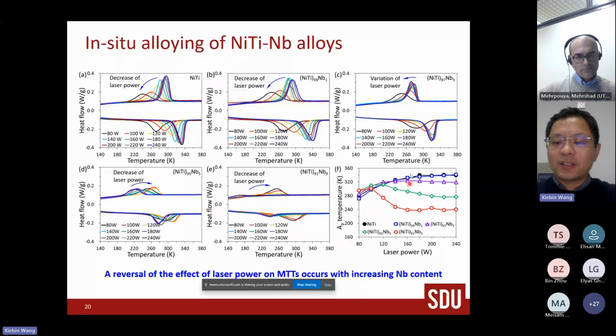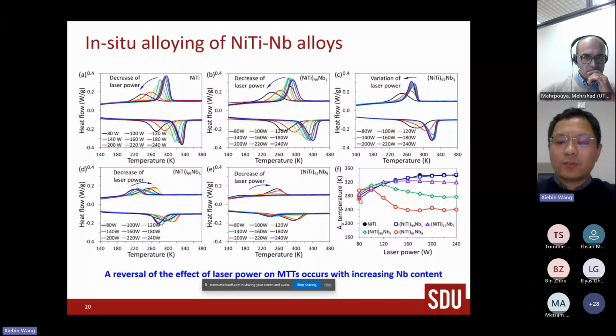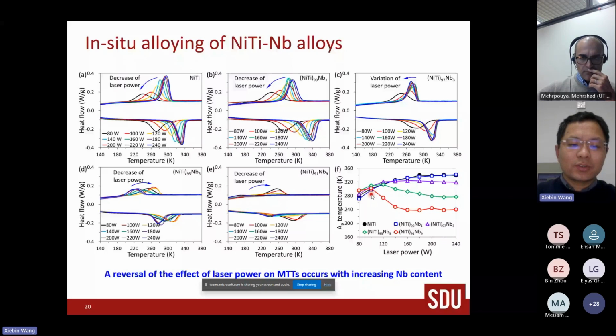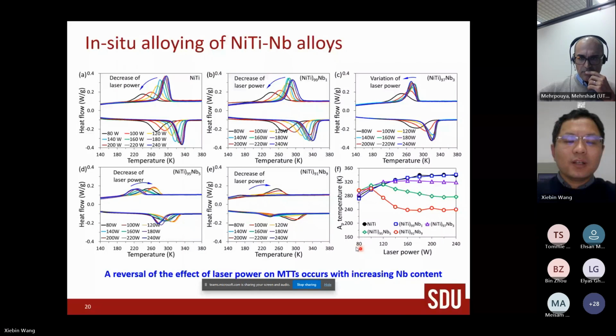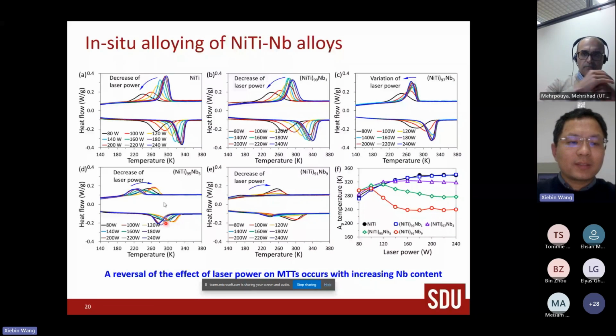So if you look at the last figure, it's clear that for the low niobium addition samples, transformation temperature increases with laser power, and for high niobium content samples, the transformation temperature decreases. That means a reversal of the effect of laser power on martensite transformation temperature occurs with the increase of the niobium content. And why does it happen, and what is the mechanism behind this phenomenon?